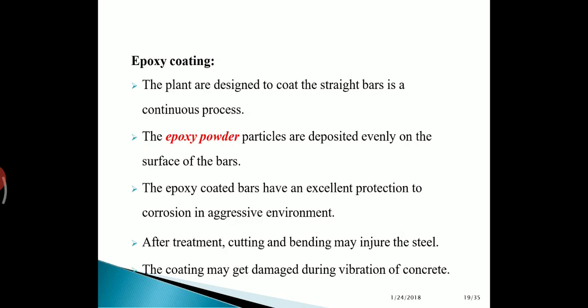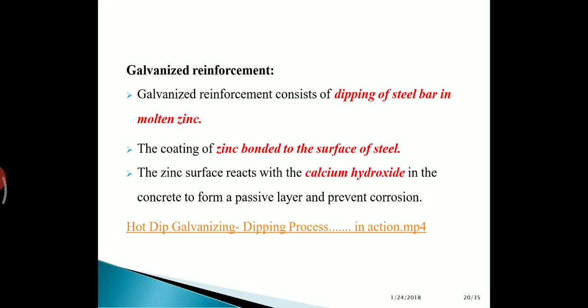In the epoxy coating, the plants are designed to coat the straight bars in a continuous process. The epoxy powder particles are deposited evenly on the surface of the bars. Then the epoxy coated bars have excellent protection to corrosion in aggressive environment. After treatment, cutting and bending may injure the steel. The coating may get damaged during vibration of concrete. Then galvanized reinforcement. The galvanized reinforcement consists of dipping of steel bar in molten zinc. So the coating of zinc is bonded to the surface of steel. The zinc surface reacts with the calcium hydroxide in the concrete to form a passive layer and prevent corrosion.